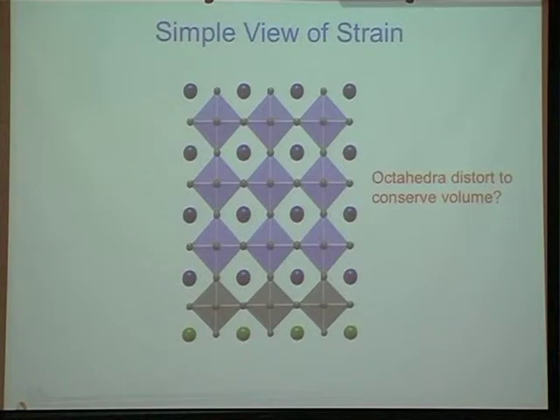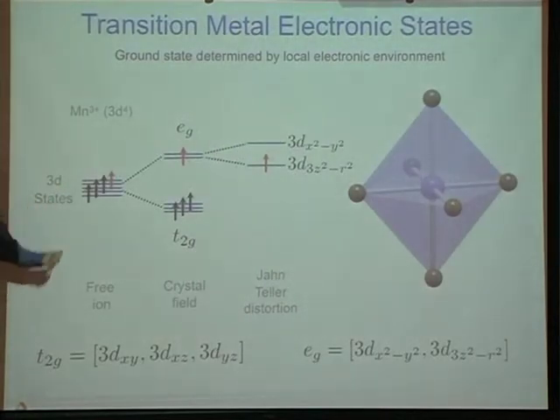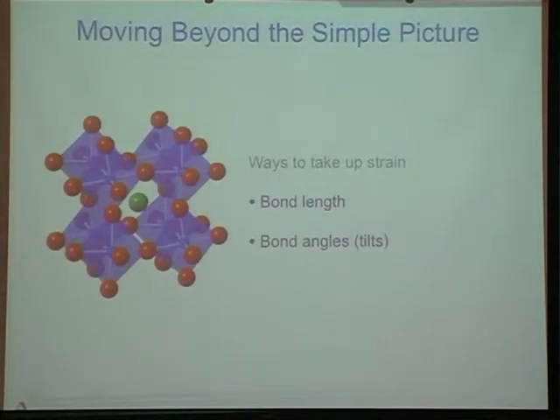So if it squishes out of a plane, then I can think of strain in a very simple way. If I'm trying to control orbitals, life becomes very good because I simply have an octahedra that I'm stretching or squishing, and correspondingly, I can move these electronic energy levels around. So sounds great. We start this experimentally, and then the first thing we have to learn is that, well,